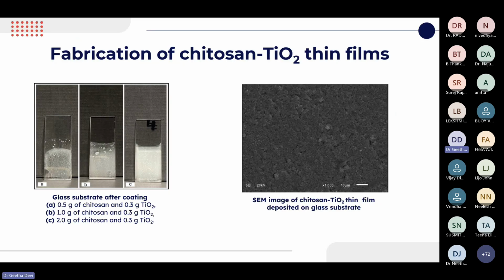This is the image of the chitosan titanium dioxide thin films with different compositions. We could see that in the first slide the coating is not proper, where we used 0.5 grams of chitosan and 0.3 grams of titanium dioxide. In the second case, the amount of chitosan has increased, and the third one is 2 grams of chitosan. In all these three cases, the amount of titanium dioxide was fixed at 0.3 grams. And the film was characterized to see the surface morphology.